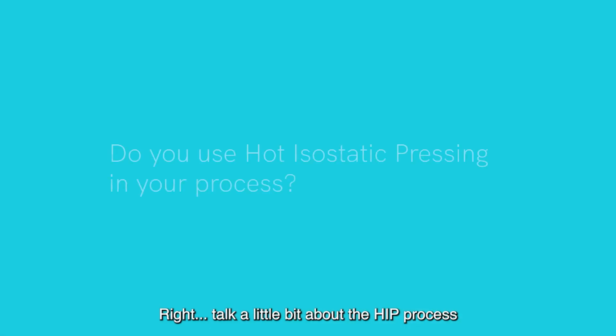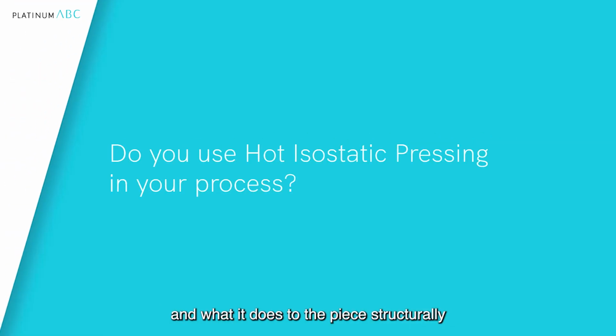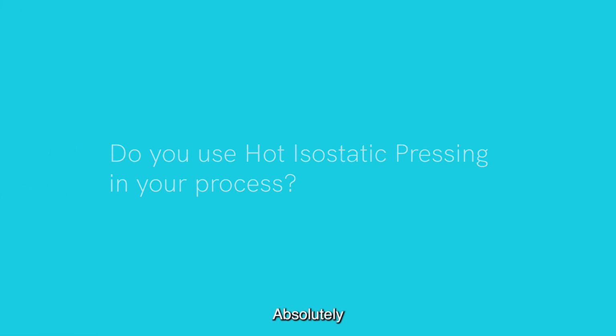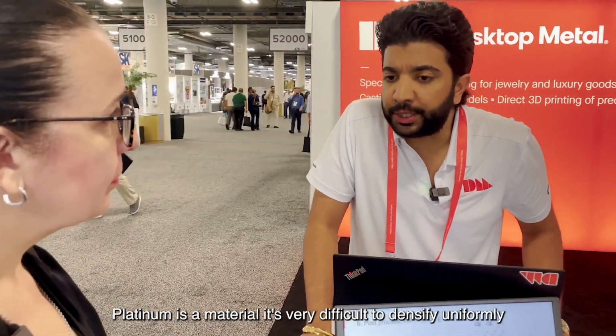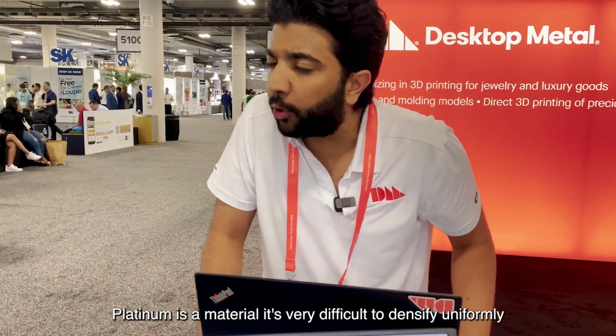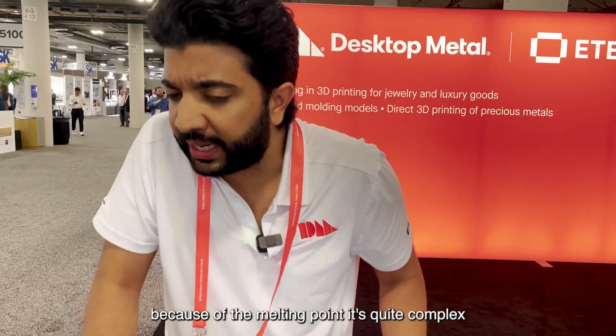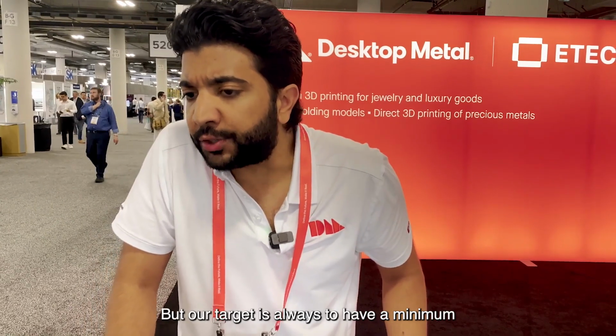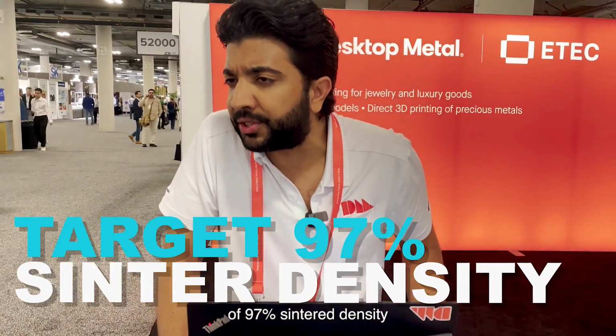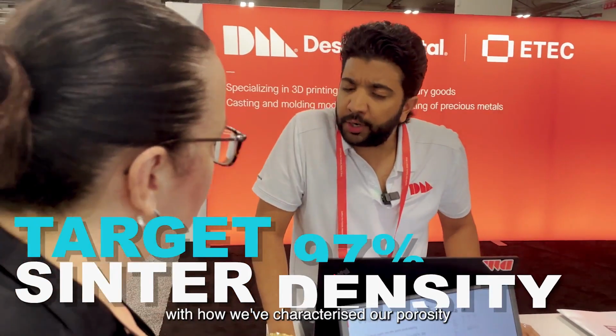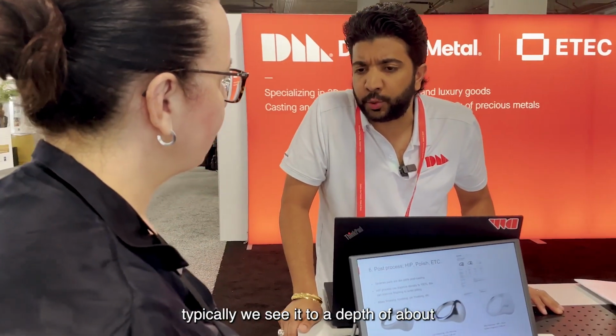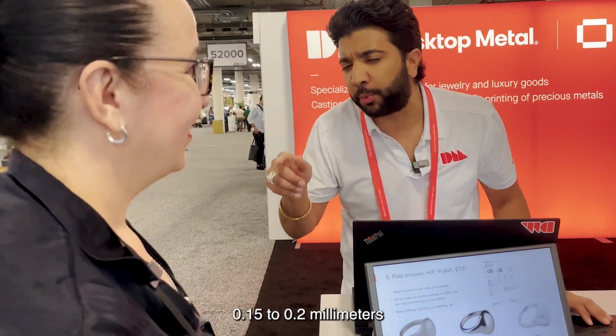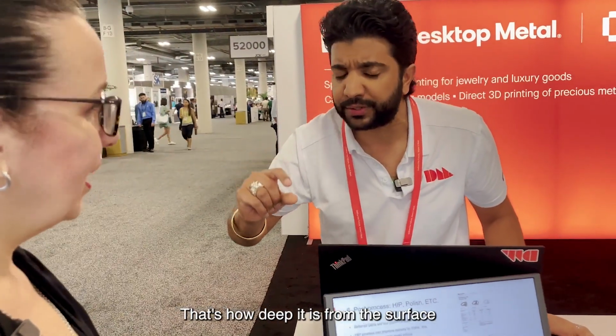Right. Talk a little bit about the HIP process and what it does to the piece structurally, but also to the surface finish. Absolutely. HIP is very important, especially in the case of platinum. Platinum is a material that's very difficult to densify uniformly because of the melting point. It's quite complex. But our target is always to have a minimum of 97% sintered density. With how we've characterized our porosity, typically we see it to a depth of about 0.15 to 0.2 millimeters from the surface. But it's well dispersed. It's not concentrated.